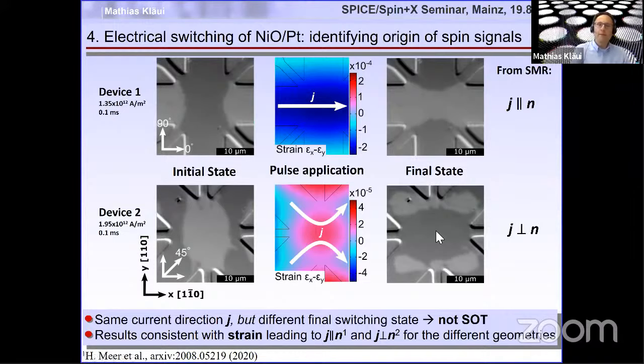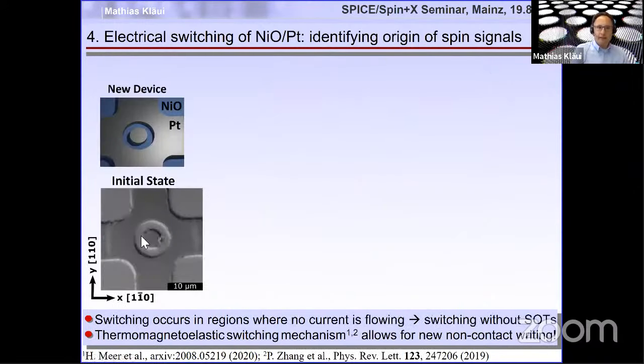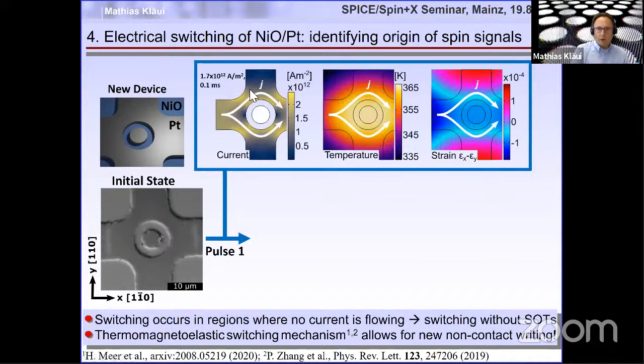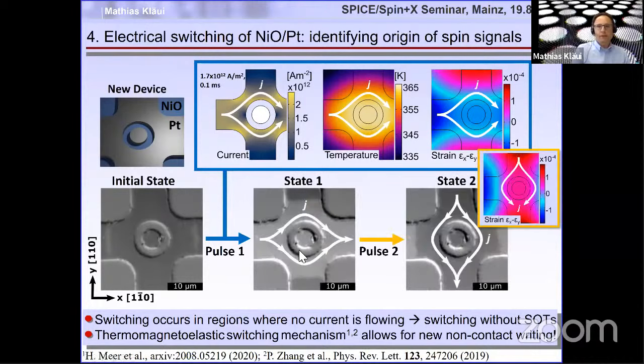But to unambiguously demonstrate this, we simply pattern now a disk in the center where there's no platinum around it. So the current is flowing only around this disk. So there's no current flowing here in the center. And let's see. We can actually still switch the center. So this means the disk here in the center has not seen any current flow, but is still switching, which means it cannot be spin orbit torques. And so this is likely then a thermomagnetoelastic switching mechanism, as we have analyzed in this paper, which is also on arXiv.